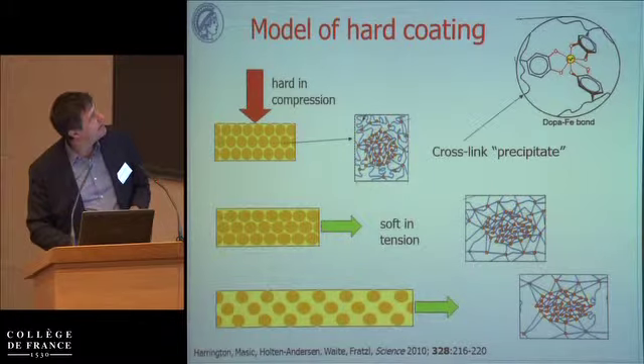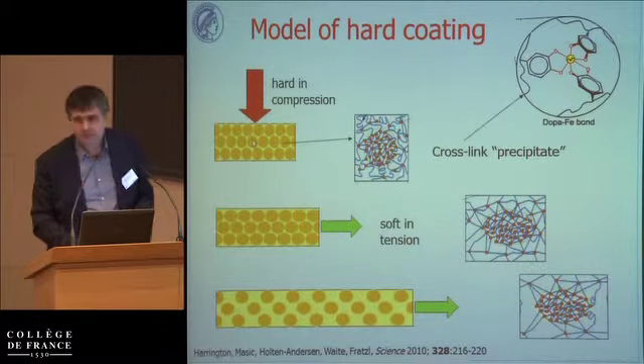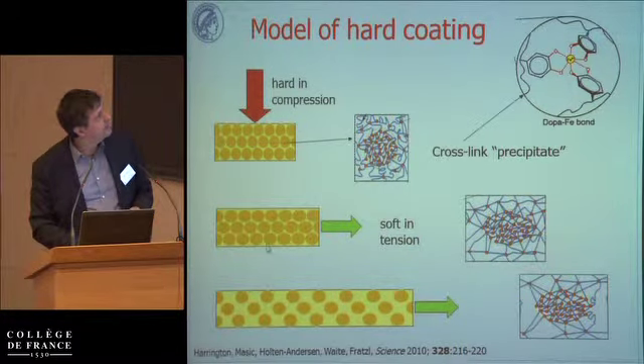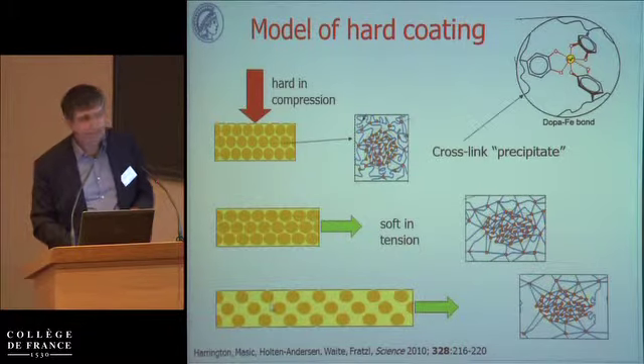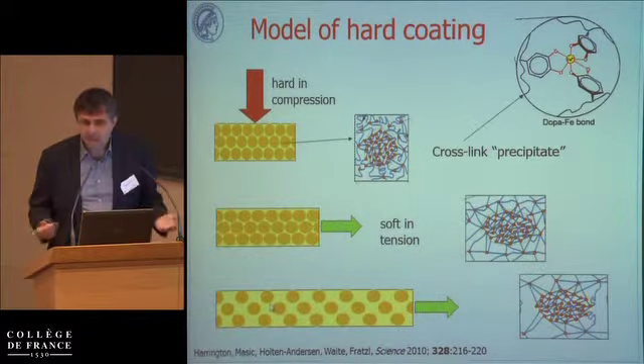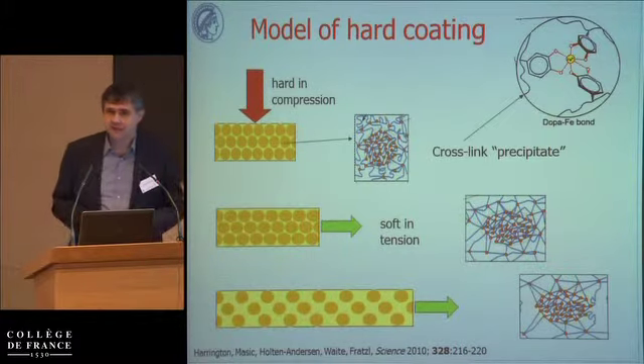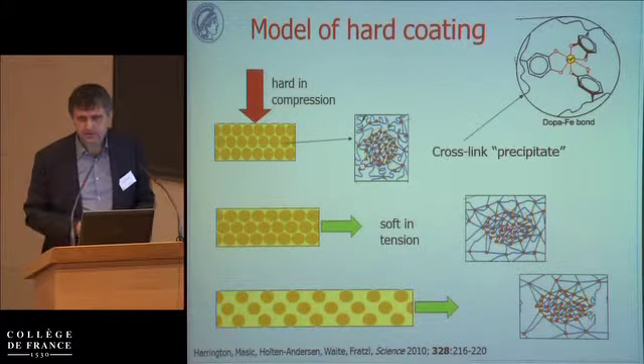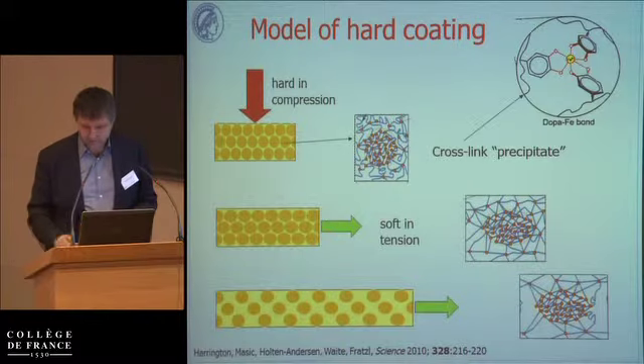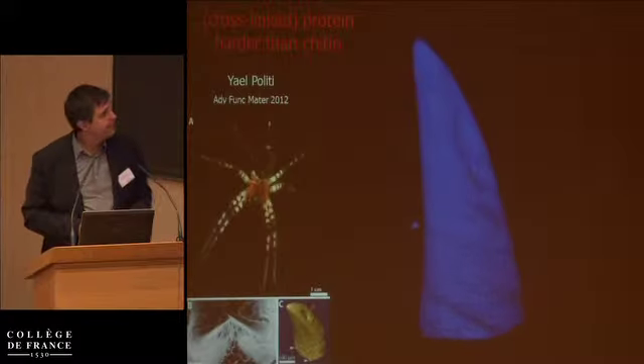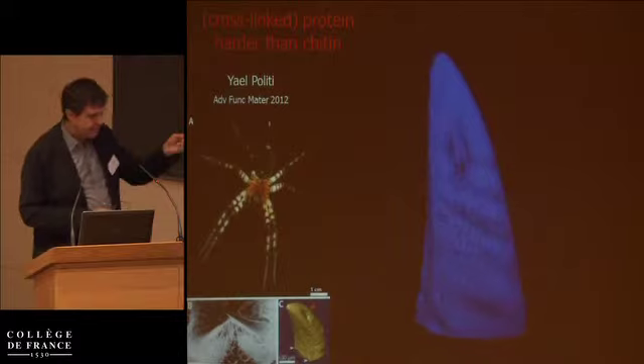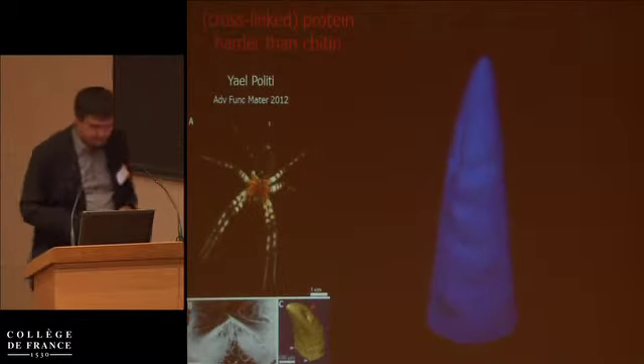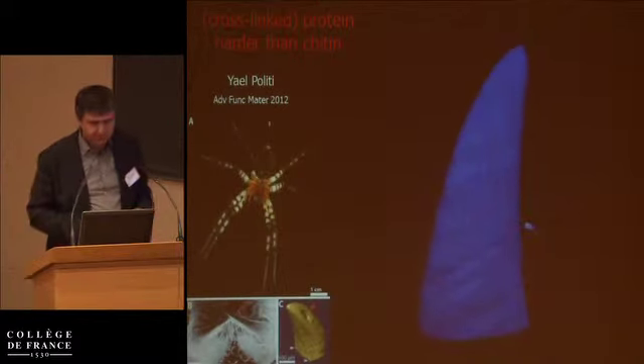Now, why is this hard in compression? Well, if I have lots of little balls here and I push on them, one ball hits the other ball, so this is pretty hard. However, if this goes in tension, the ball is hardly deformed. What deforms is the matrix in between the balls. And therefore, here's an extensible material that's hard in compression and therefore suitable as a wear-resistant coating for an extensible fiber. Now, this is work from Yael Politi in the lab,